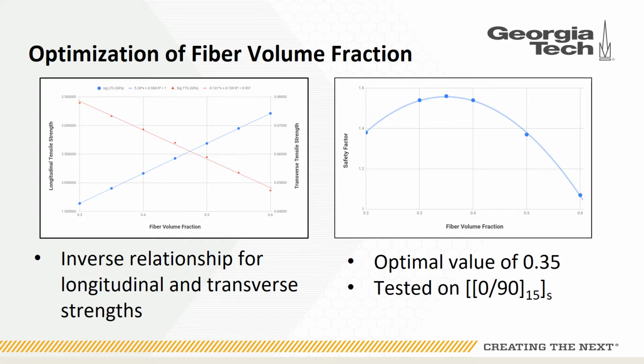For the exact value, the figure on the right shows a plot of the safety factor as a function of the fiber volume fraction. A higher safety factor corresponds to a laminate with higher strength. Therefore, safety factor is a value that the team wanted to optimize, so fewer plies would be needed, resulting in overall lower thickness. A value of 0.35 for the fiber volume fraction gave the optimal safety factor, peaking at 1.56, and was therefore chosen as the value for VF.